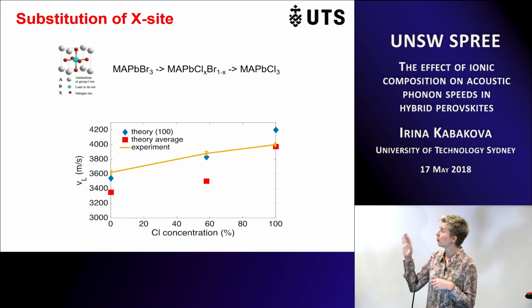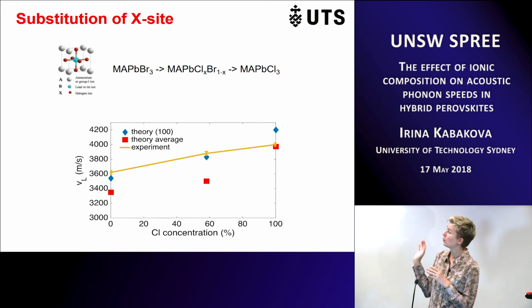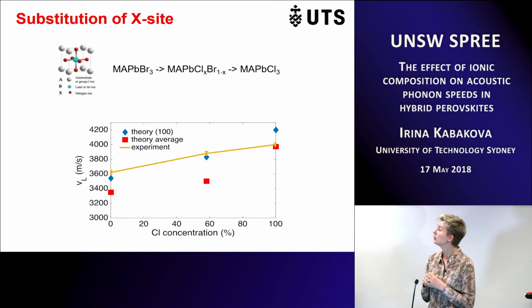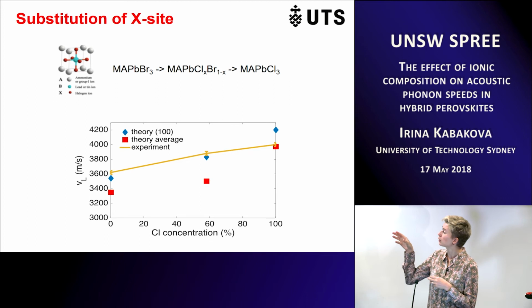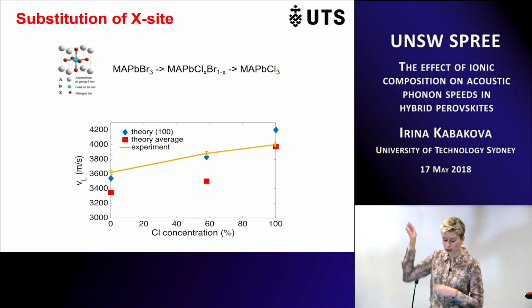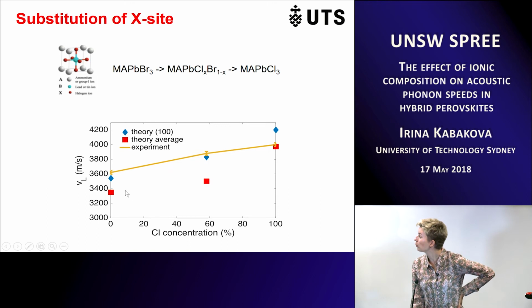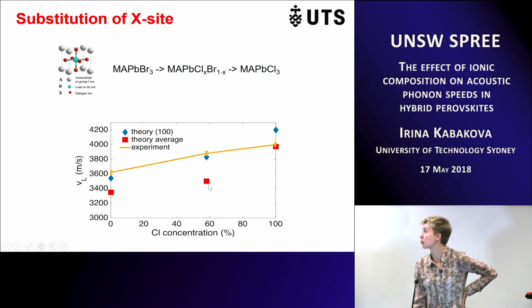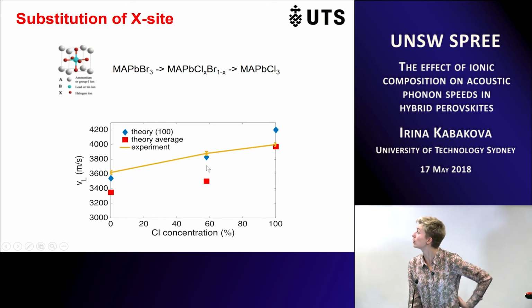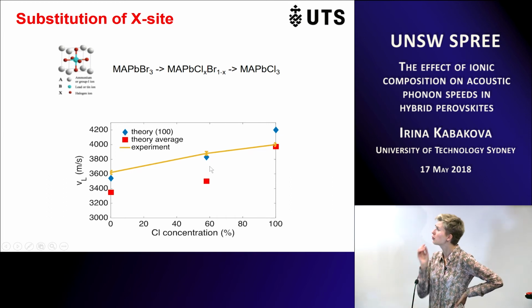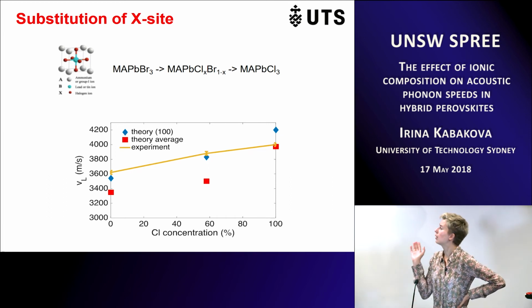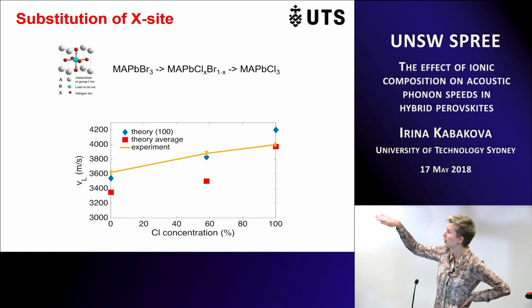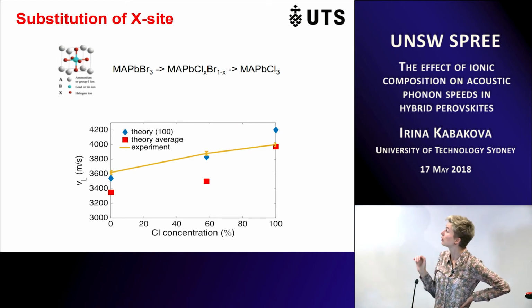So essentially, let's look first at substitution of the X site, which is the halogen atom. We go from bromide crystal through the mixture to chloride crystal, and that's what our data is showing. The yellow one is experiment, the red squares is theory averaged across all directions, and the blue one is theory along a principal axis. The agreement is there, especially with the theory along the principal axis 1, 0, 0.